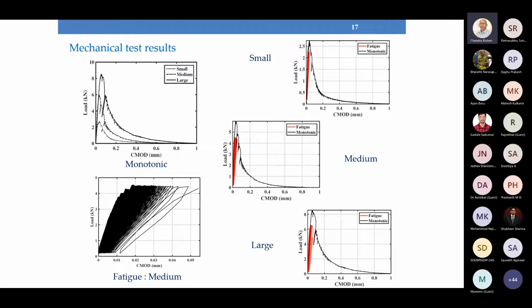Now, for each of the small, medium and large beams, we have the static response, shown by the dark black curve, and the fatigue response on the same size specimen is shown in red. Under fatigue loading, the final failure occurs with a very small CMOD at failure, compared to the CMOD in a monotonic static case. Here approximately 0.8 to 1 mm is the CMOD at failure in a static test, but in fatigue it is much, much smaller. In most of these cases, the static curve serves as an envelope to this fatigue response.